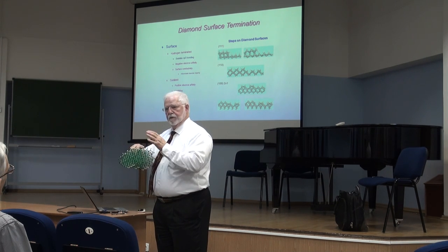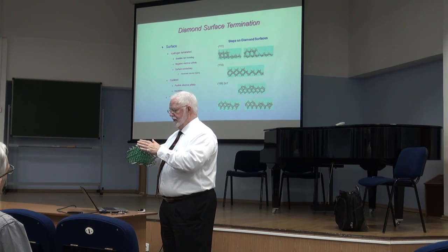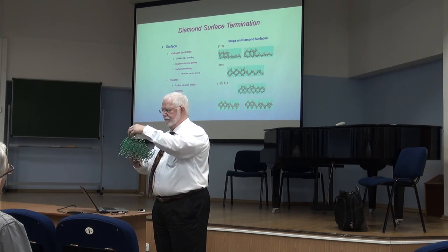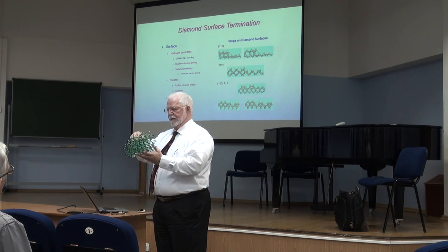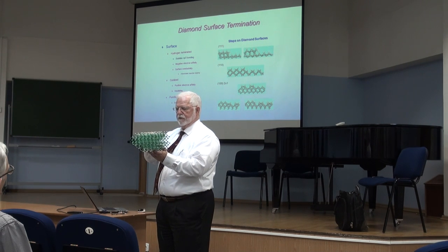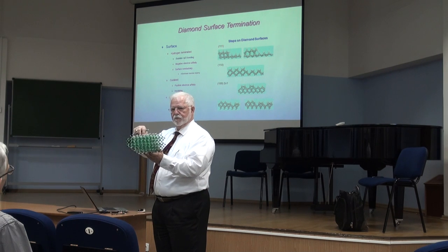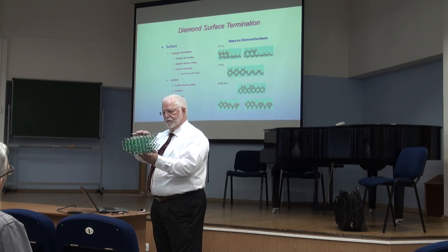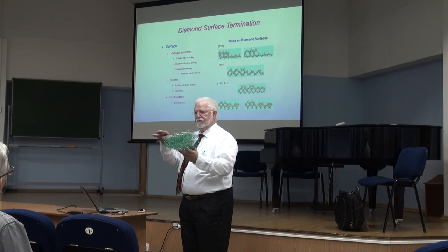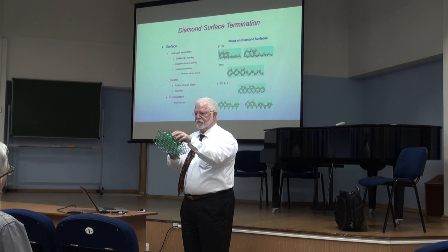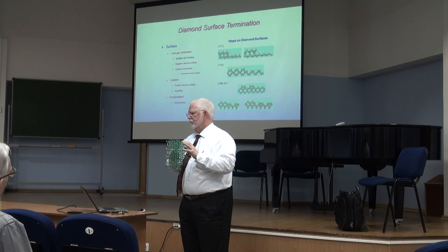If you try to put another atom there, say fluorine or oxygen or chlorine, they're too big. They can't bond to every single carbon. Even hydrogen can't do that, and that's why this particular surface has a reconstruction where I've shown these dimer bonds that form because the hydrogens were too close together. We call this the 2x1 reconstruction of the (100) surface. So you can think of diamond with its complex surfaces, and I show several different examples here, all covered with C-H bonds.